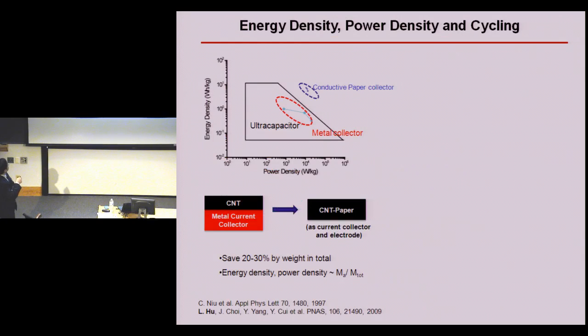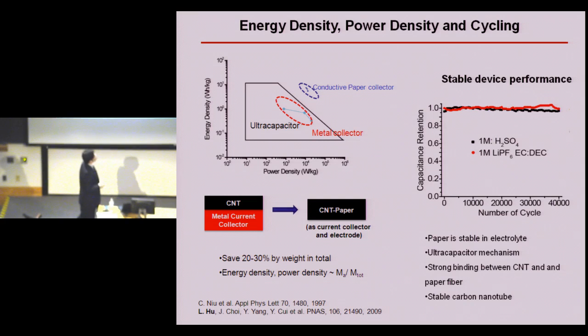So in the end, we would like to have a comparison of energy density and power density with other kinds of devices. Because conductive paper is much more lightweight than the metal-based current collector, we can see here we save weight because of this lightweight conductive paper. So in the end, we enhanced the energy density and the power density because of the light weight of the conductive paper as well.